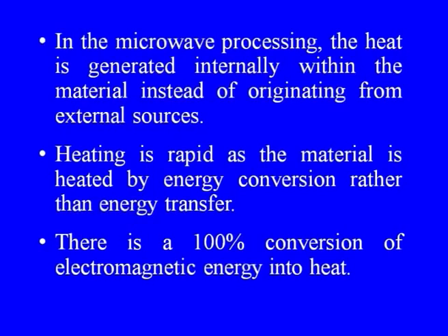In microwave heating, heating is rapid as the material is heated by energy conversion rather than energy transfer. This is what we have discussed now. In conventional heating, it is rather energy transfer from molecules to molecule, but here this is rather energy conversion from electromagnetic form into heat form.